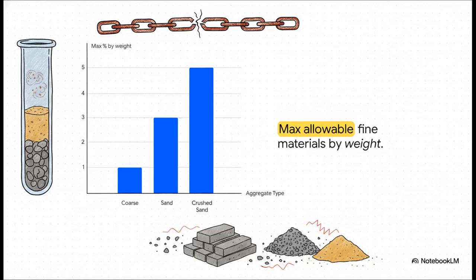Going back to that clay test for a second, it really all boils down to the weakest link. Even a tiny, tiny fraction of a percent of clay can fatally compromise the aggregate strength because it stops the cement from actually bonding to the rock. The limits are crazy strict. A max of 3% fine materials in regular sand, 5% for crushed stone sand, and a microscopic 1% for coarse aggregate. If it's even a fraction over that, the recipe is pretty much doomed.